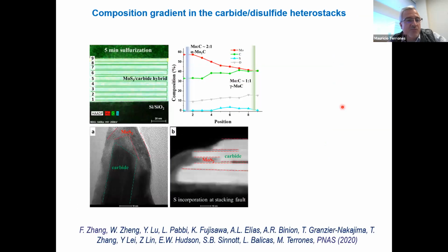So this is what we have seen. What happens is that the carbide starts being transformed from the edges, and the H2S, you have stacking faults, and the H2S diffuses very rapidly along these stacking faults, and that starts transforming the molycarbide into molysulfide. But before that, it creates a sort of monolayer of gamma prime molycarbide.